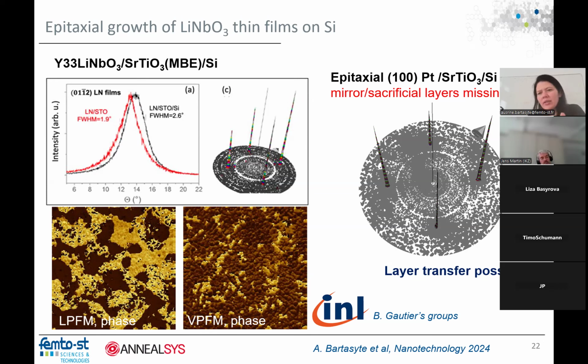Now, we show that it's possible to do a layer transfer. So it would be possible to use this template and to do a large-scale lithium niobate 012 orientation, or Y33 orientation, transfer on big substrates. We show also that the film, of course, as it's grown and the substrate is non-ferroelectric, had ferroelectric domains, plus and minus. And we had 4 orientations in the plane because strontium titanate is cubic, and this orientation of lithium niobate is pseudo-cubic. So it's not 4 equivalent axes, you have just one single polarization axis. Here you see the C-axis pole figure, so we have 4 orientations in the plane.